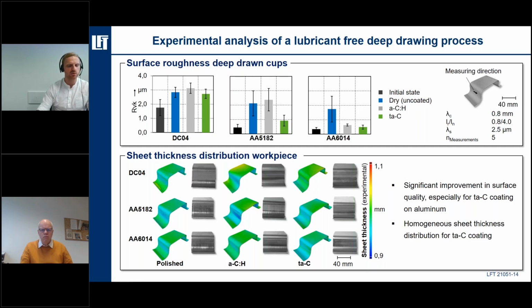The reasons for improved tribological behavior for the ta-C coatings might be the extremely high hardness of the tool coating, like Professor Hagener told before. In particular, hard materials tend to be less prone to adhesion since the amount of metallic bonding forces is significantly reduced at the blank die interface. Furthermore, the ta-C coatings reveal a good layer adhesion with a high abrasive wear resistance. From a research objective, the use of ta-C coatings is more effective, although the application is quite more difficult.